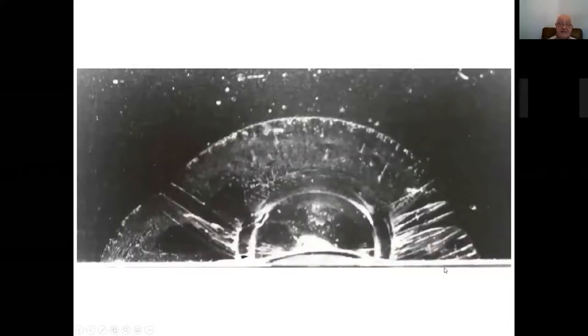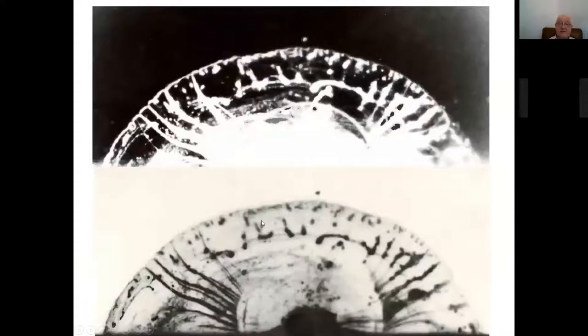So what this tells you is that a crack growing naturally will accommodate its shape, trying to get a uniform distribution of the stress intensity factor around the crack front. And in some cases, as you can see here, you had this kind of angular point in which this growth towards the surface was evidently done at a certain moment after, once again, eliminating mode 3. Again, two different positions, two different light adjustments for the same crack. Why? Because in some cases you had some non-regular crack front, so this means that you had this kind of irregularities, again coming into one of these striations, as you can see here.